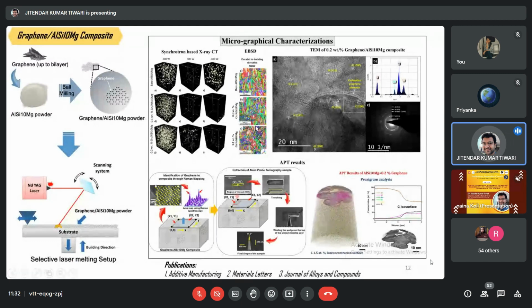Tomography is basically taking a picture in 3 dimensions, and we are identifying the pores available inside the metal, and whether they are irregular pores, small spherical pores, or big spherical pores, that we must be able to understand. Here we can see the variation in the pore fraction as well as morphology. The morphology here is irregular, then it is small spherical, and then it is increasing. So basically we can achieve this kind of gradation if we vary the laser parameters.